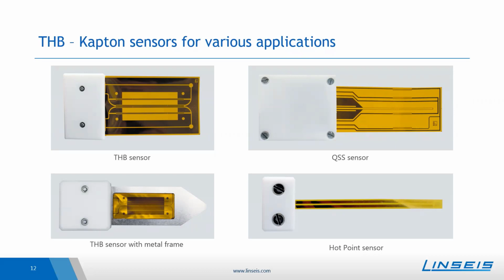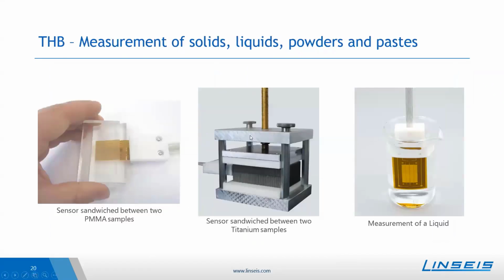Further questions concern the roughness of the sample surface. As mentioned before, to be able to have a very good sensor sample sandwich, one needs to press the configuration together. And a very rough sample surface can then damage the sensor foil. So there are no strict or defined requirements regarding the sample surface. One just needs to make sure that when the sensor touches the sample, it should not be too scratchy, too rough, so that the sensor foil can be damaged.